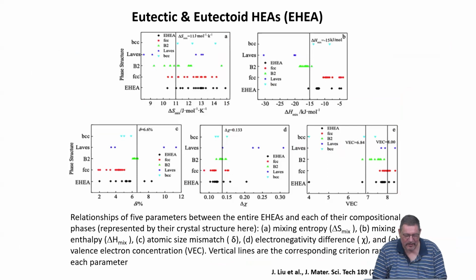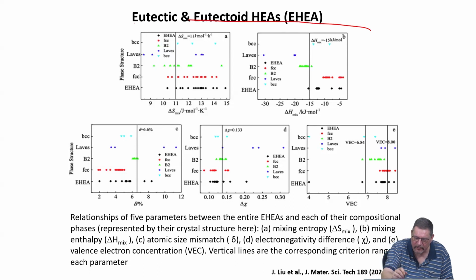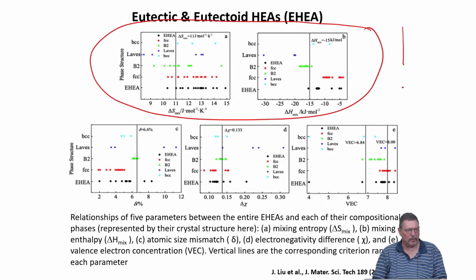And then these are some relationships about different criteria and where to find the eutectic high entropy alloys, as compared to other competing phases which are typical in these systems that form eutectic high entropy alloys. The quintessence of this is, delta H, delta S work nicely, otherwise systematics are poor, but statistics are poor anyway, because there are not so many eutectic high entropy systems which have been reported and investigated so far. So far as of today, these are the important criteria and conditions if you are looking for eutectic high entropy systems.